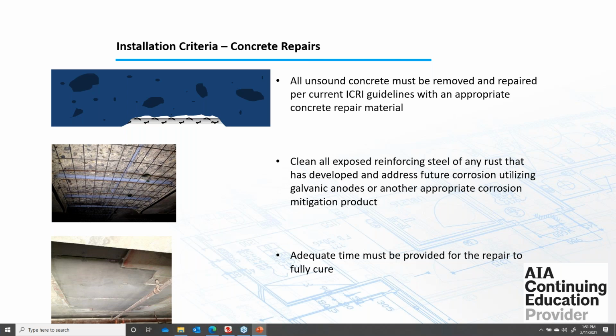So before installing the selected FRP system, all unsound concrete must be removed and repaired per ICRI guidelines using appropriate concrete repair material and methods. If there was corroded steel rebar, it is highly suggested to expose it, clean it, and protect it against future corrosion using appropriate solutions such as galvanic anodes or corrosion inhibiting coatings like the blue one we see in the middle picture. Once repair material is applied, adequate time must be provided for the repair to fully cure. Next slide, please.